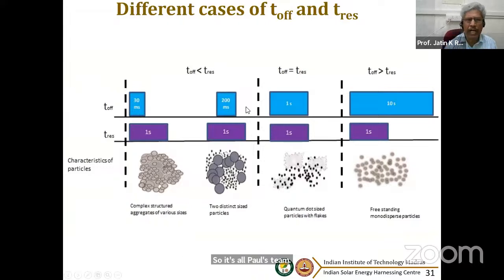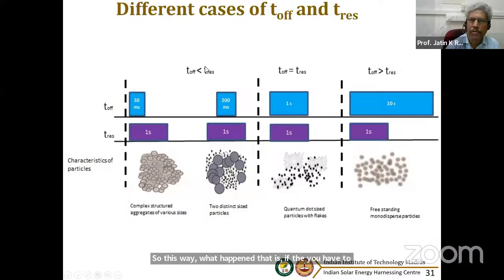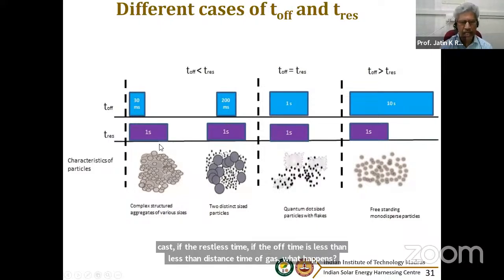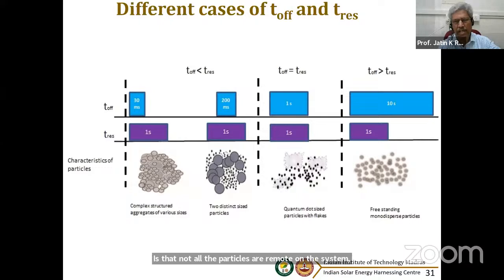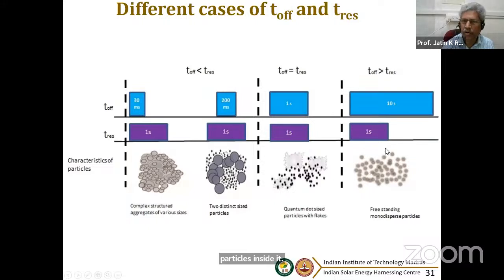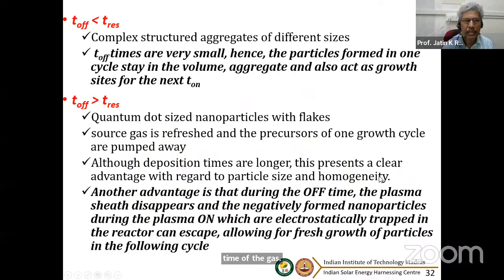So this way, you have to keep the off time more than the residence time of the gas. If the off time is less than the residence time of the gas, not all the particles are removed from the system. Those particles will remain in the plasma zone and will start growing, so you get different types of particles inside it. Whereas if the off time is more than the residence time of the gas, you get homogeneous monodispersed particles here. So that's what is basically written down here.